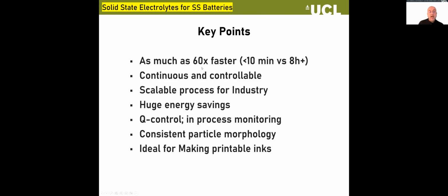So the key points here are that you're going essentially to under 10 minutes. By the way, the conventional synthesis of LLZO is usually, well, it's many hours and many heats and grinds, so it's probably more than 8 hours. I put 8 hours, probably because I just copied it from another slide, but it's a solid state reaction generally in industry. Obviously, the advantages here is this is highly scalable, and we were getting up to semi-kilos per day, or certainly kilos per day scale.